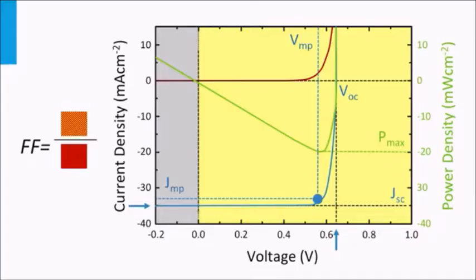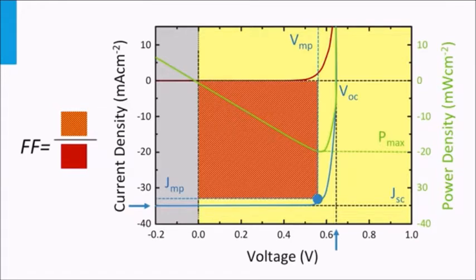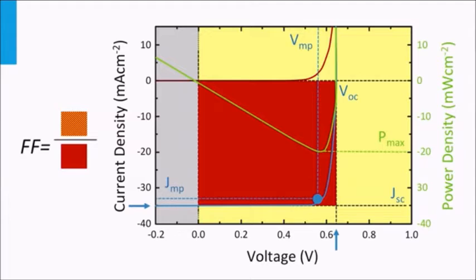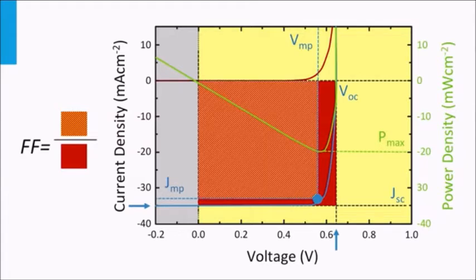The fill factor can be easily visualized in a JV curve. Basically, the fill factor is the ratio between the area shaded red-yellow and the red area. In other words, the fill factor is the ratio between the rectangle with sides VMP and JMP and the area with the sides of the open circuit voltage and the short circuit current density. This means that we can express the maximum power density as a product of the fill factor, the open circuit voltage and the short circuit current density.